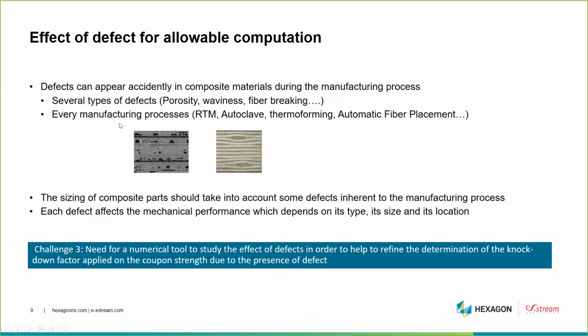So no matter the manufacturing process, we know that there is some defect in the composite. And we know that the sizing of the composite part, or let's say the value that we use for the sizing, should take into account the presence of those defects that come from the manufacturing process. And each defect will affect the mechanical property, which depends on the type of the defect, the size of the defect, and the location on the coupon.